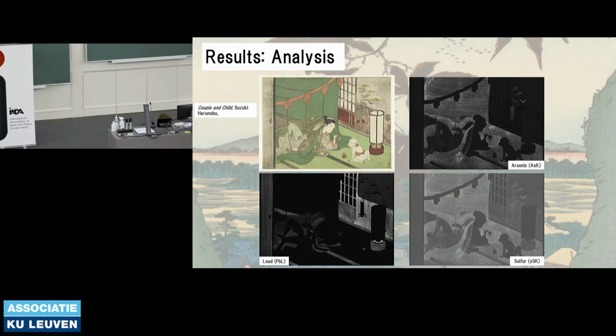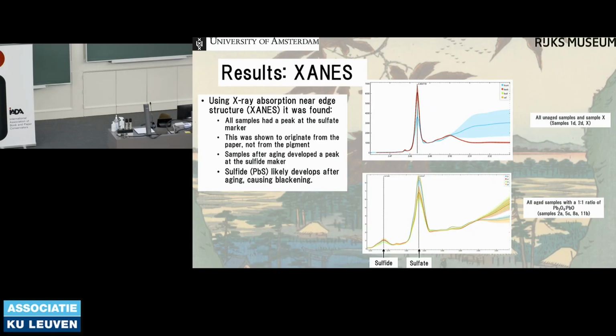As stated previously, when tested, both X-ray diffraction and Raman spectroscopy were able to identify the existence of red lead, but were not able to identify the identity of the discoloration, likely due to the thinness of the layer apparent and its amorphous nature. While it was disappointing that these methods did not work, all was not lost. Shortly after I finished my thesis, I got a chance to have XANES and micro-XRD analysis performed by Marine Cotte and Clément Hall at the European Synchrotron Radiation Facility.